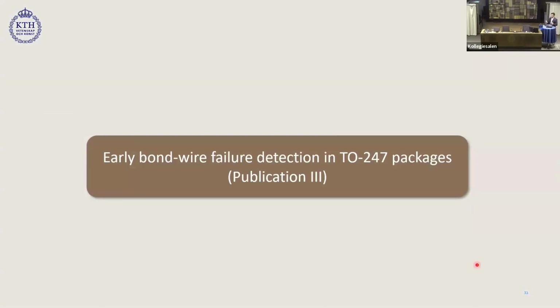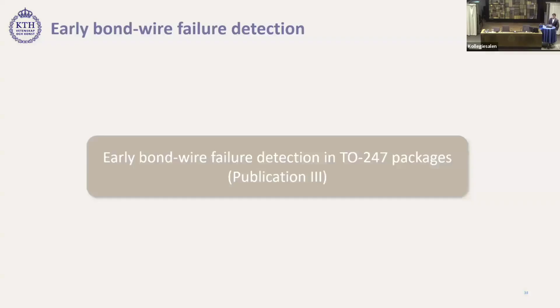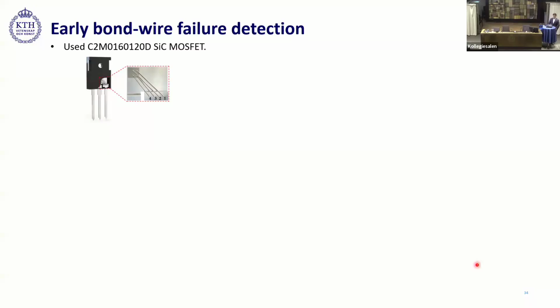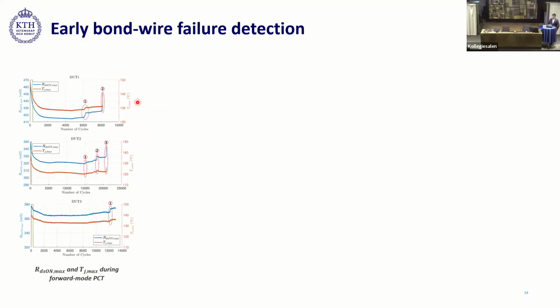We used the same method in the device with multiple bond wires and proposed that this can also be used for detecting bond wire lift-off events in the package. So here we use the data from degrading these Wolfspeed devices which have multiple bond wires. The process is the same. First, we take the RDS on max and TJ max values from the power cycling test. Here we use 3 devices. In the highlighted circle region, we see that the RDS on max is increasing in steps, and each step basically represents a bond wire liftoff event.